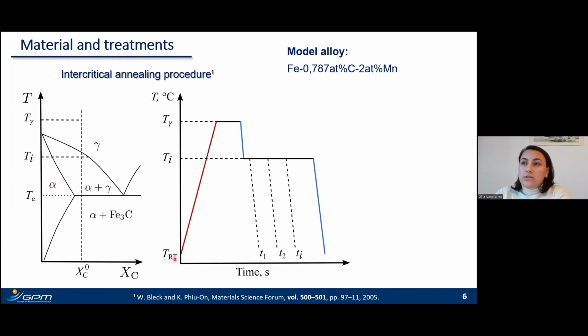So in this work, we investigated an iron-carbon model alloy with approximately 0.8 atomic percent of carbon and 2 atomic percent of manganese. The material was treated with an intercritical annealing procedure that's schematically shown on the slide, and mainly consists of 3 main steps. First, austenitization, when the material is held at high temperature to obtain a fully austenitic structure. Then it is cooled down to a selected temperature from the alpha plus gamma region above the eutectoid temperature and held isothermally for some defined time.